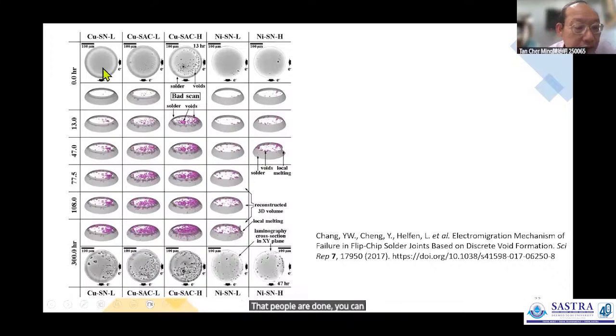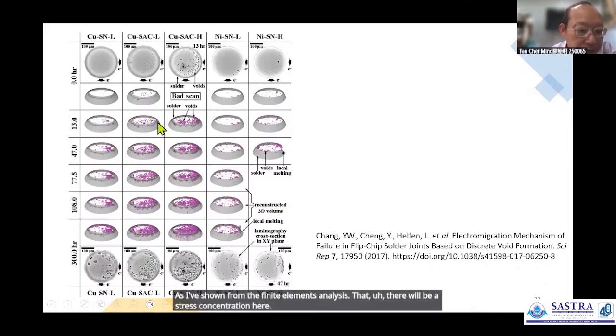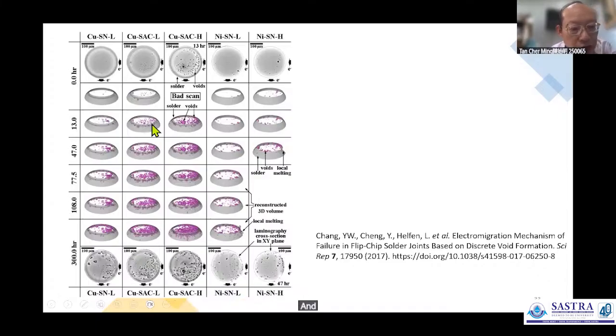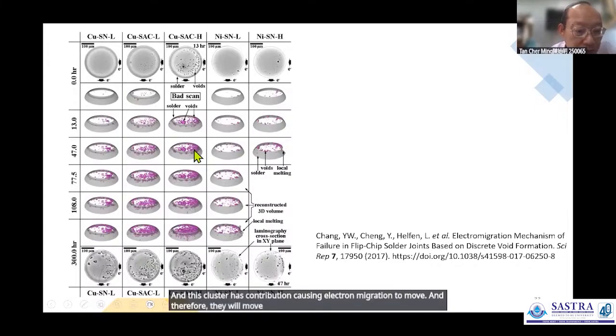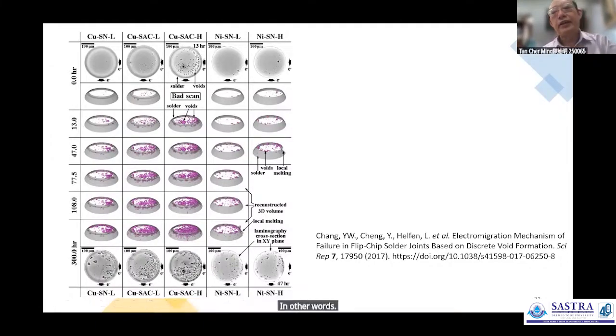You can see that for different types of copper and different types of solder, as you go in time from 0 hours to 300 hours, the damage is always at the corner side, as I showed from the finite element analysis, where there is a stress concentration. This stress concentration causes electron migration to move inward toward the center. In the end, you're causing an open circuit. In other words, the solder is there, but there's no electrical connection. So it will happen in 300 hours, not long.